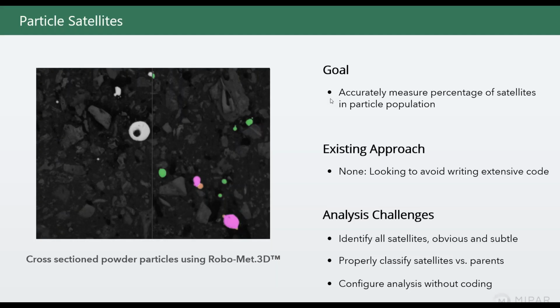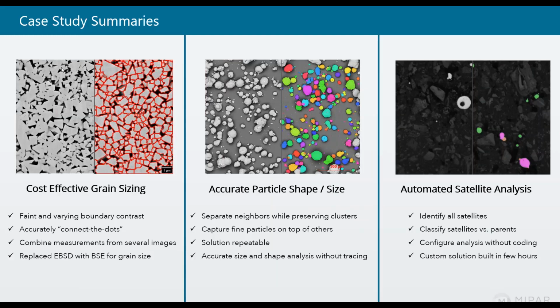First case, they were using EBSD imaging just to collect a grain size distribution. It's the only thing that could reliably find the grains. It took them about 10 hours a sample. They were able to use a MIPAR solution, replace their EBSD imaging with backscatter imaging, which took a minute per image, and process a load of 240 samples in a day instead of 4 months. The cost and time breakdown and calculations are described in much more detail in the cover article that is in the handout section and that we've mentioned before.